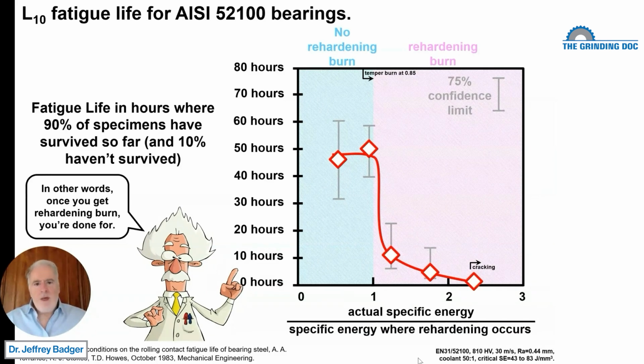That's a big drop. Then if he was even more abusive and got even deeper rehardening burn or higher temperatures, here he did it in terms of specific energy, that gets a little complicated, the specific energy over the specific energy where rehardening burn occurs. But let's just say he exceeded the rehardening burn threshold by a lot, and therefore got deeper rehardening burn. Then his fatigue life dropped down to 2 or 3 hours.